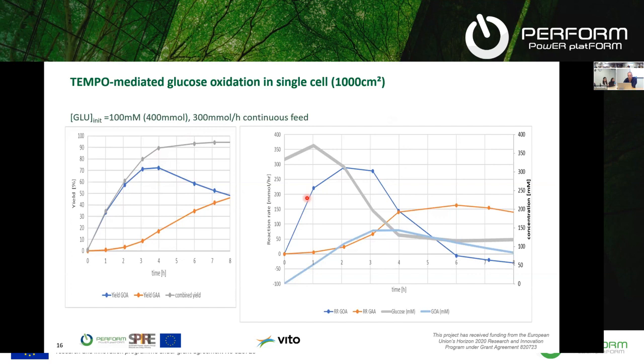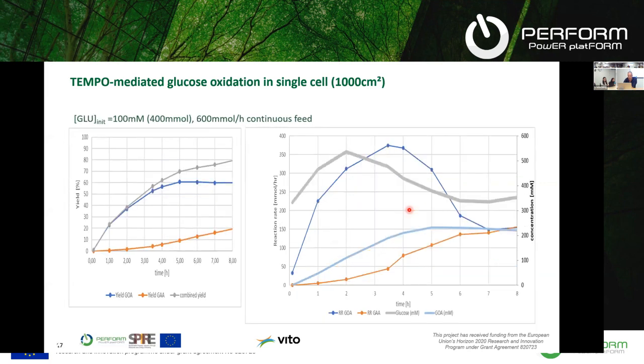When we look at reaction rates, we see that especially the rate of the gluconic acid, so the monoacid, follows a lot the glucose profile, of course, the glucose concentration, and the reaction rate of the glucaric acid actually starts to increase when gluconic slowly is decreasing after some time. It takes more time for the glucaric acid to form. We did the same experiment also for a continuous feed at 600 millimoles per hour.